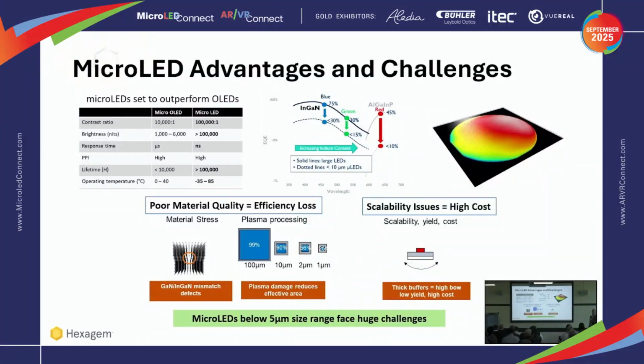In planar materials, when you grow buffers, you need rather thick buffers to get the material quality up. And that, of course, again introduces strain between the silicon or sapphire and the GaN buffers and creates dislocations. But also the thermal expansion mismatch to the wafers causes wafer bow and can result in low yield in follow-on processes. So it's mainly the material quality and the fact that we can get around wafer bow issues with our technology that I will talk about today.